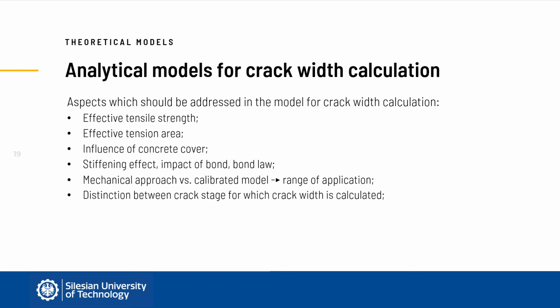Distinction must be made for which crack stage calculations are made, and preferably calculation procedures should be differentiated to account for different behavior of cracks in the crack formation stage and stabilized crack stage. Distinctions should also be made for cracking at early age and in the long term during service life. The conditions for which cracking may occur during hardening of concrete are different than in the case of mature concrete.